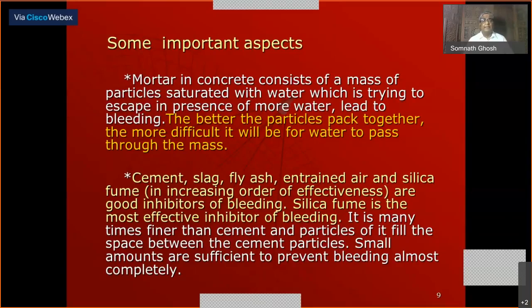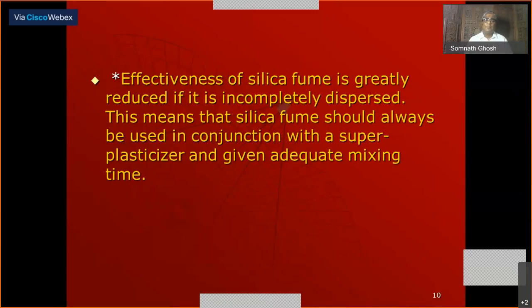It may be many times finer than cement, even 10 to 15 times finer than cement particles, and it fills the space in between the cement particles. A small amount is in many situations sufficient, but an excess amount is not really required. It is costly also. The effectiveness of silica fume is greatly reduced if it is incompletely dispersed. This is very, very important. Those who are manufacturing RMC should know, because high performance concrete, in the presence of these admixtures, plasticizers, RMC is the place where they can manufacture it easily. This means that silica fume should always be used in conjunction with a superplasticizer and a given mixing time. So you have to mix it, add it in, you have to give some time.